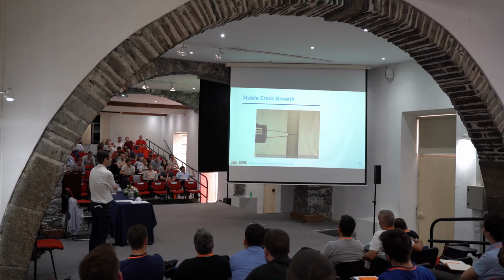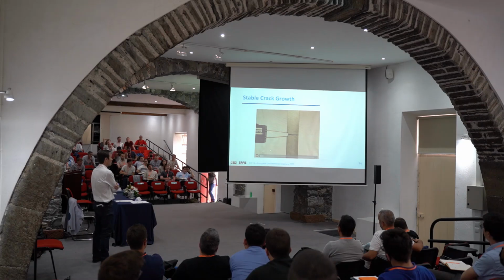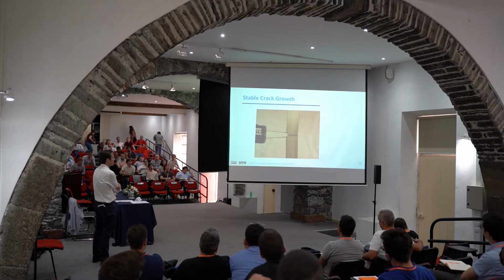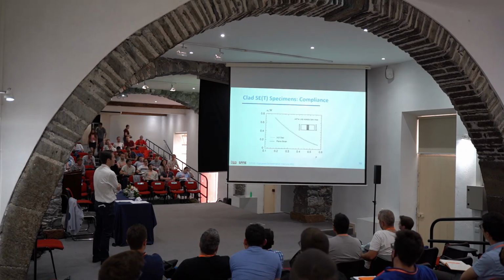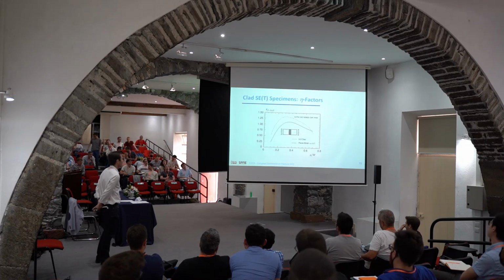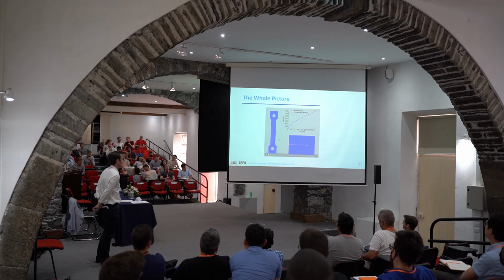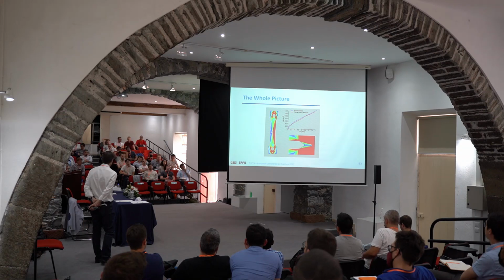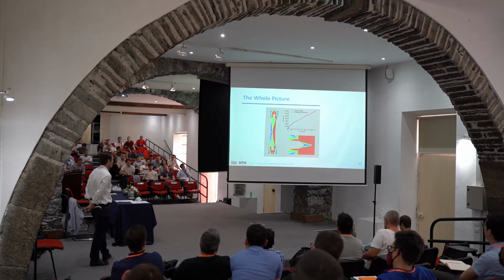Just to give you an idea how the test is conducted, you are going to see the unloading. It's not fatigue, no fatigue loading. This is increasing load, just in one load. Let's stop it. Here the crack is propagating, you see here. These are details about all the parameters that we evaluate. Let's skip this. Just to give you an idea what enters the assessment. You can see here the crack is growing, and nowadays, for those more interested in numerical prediction, we have very good numerical tools to predict the damage criteria in this kind of material.